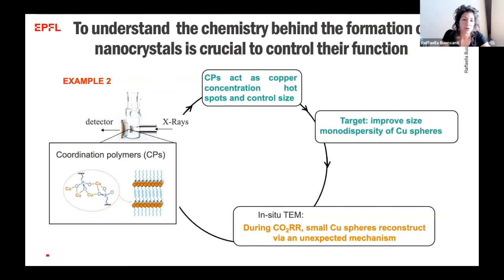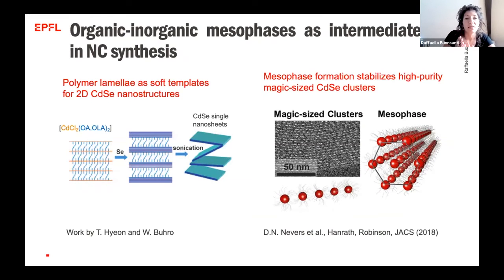So this is the second story that I wanted to share with you, where we did find that the intermediate is this coordination polymer, and we suggest that this coordination polymer acts as a hotspot and therefore allows a burst of nucleation and eventually monodispersed particles. And then we were able to use these highly monodispersed particles to study how size distribution changes during CO2 reduction and eventually identify this dissolution-reprecipitation mechanism. And again, I would like to highlight the fact that these organic-inorganic mesophases as intermediates in nanocrystal synthesis have also been reported for cadmium selenide nanostructures, so might be more common than one might think.